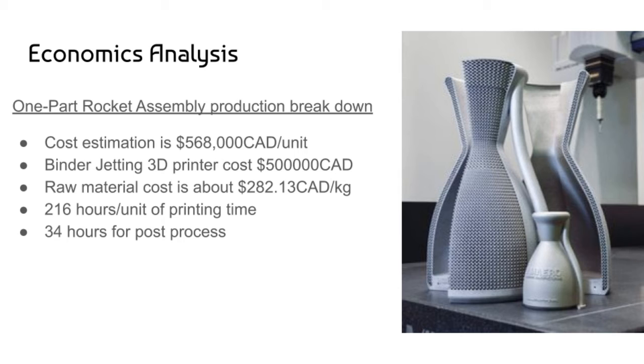Based on the specification of the printer, the total hours to print one single part using the binder jetting 3D printer is roughly around 216 hours per unit built. This is because the printer can print 1 centimeter of height per hour. As a result, it took 216 hours to completely print the whole rocket nozzle. Also, an additional 34 hours is required for the post-process after the part is printed, such as to clean the part, cure it with selective heat treatment, and also surface finish treatment. We will go in depth for the total cost estimation in the next slide.